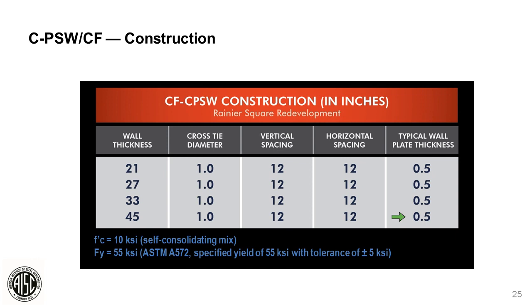There are some zones at higher demand levels where those plates were increased to 3/4 inch. And then up at the outrigger levels, there are some zones where the BRB connections and gussets come in, on the order of 2 inch. The wall thicknesses were nominally 21 inches to 45 inches, nominally 2 feet to 4 feet thick, with the largest thicknesses down at the base of the building and tapering as we moved up the building. The cross ties are 1 inch diameter cross ties that were spaced 12 inches on center, both vertically and horizontally on all wall faces.